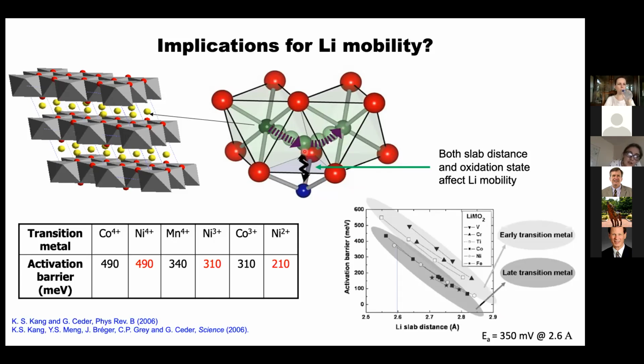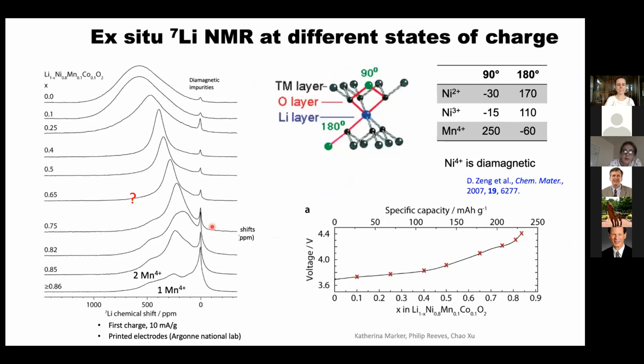And in the tetrahedral site, there's a short contact with the metal below. And so as the layer collapses and the charge of the metal goes up, the activation barrier goes up. And so you could see that these C parameter collapses would be bad for mobility. So in order to test that hypothesis, we did NMR, of course.